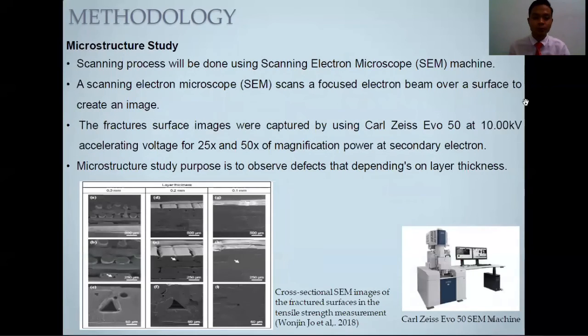Okay, lastly, the microstructure study will be done using the scanning process. The scanning electron microscope, SEM machine, will be used for this process. A scanning electron microscope SEM scans a focused electron beam over a surface to create an image. The fracture surface images were captured by using Carl Zeiss Evo 50 at 10 kV accelerating voltage for 25 times and 50 times of magnification power at secondary electron. The microstructure study purpose is to observe defects that depend on layer thickness.